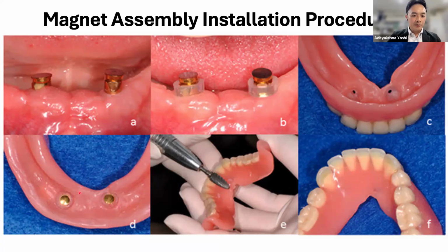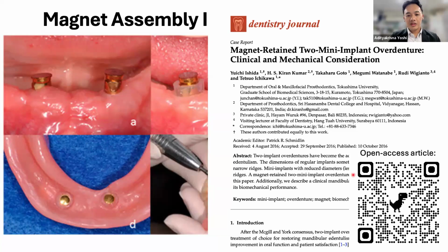And after the complete polymerization of the self-curing resin, these magnet assembly components will be picked up into the denture part. And afterwards, the excess resin on the polishing surface is trimmed, finished, and polished using the finishing and polishing burr, as we can usually use for acrylic-based denture resins or PMMAs. And this is the final prosthesis result.